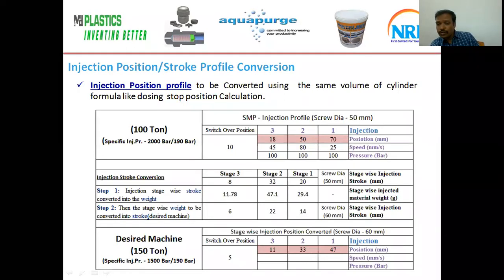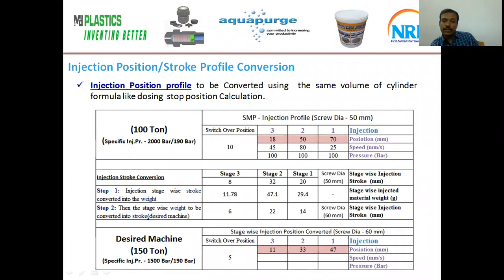Our screw dosing stop we already calculated, that is 47 mm. Then stage 1, 47 to 14, is 33 mm, so in stage 1 we are injecting 33 mm. Then stage 2, 33 to 22, is 11 mm we are injecting in the 60 dia screw. Then 11 to 6, 5 mm, is the switchover position in the 150 ton machine.